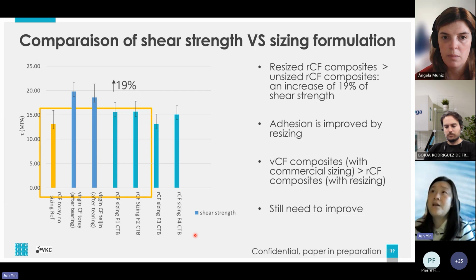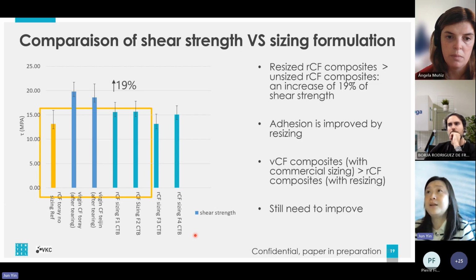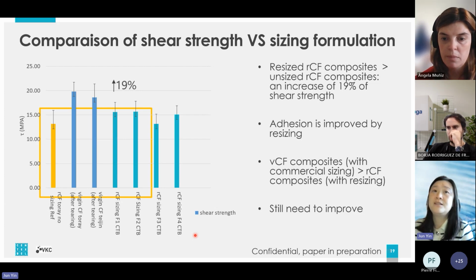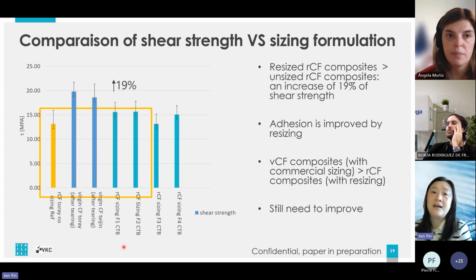The first is we can see clearly the resized recycled carbon fiber composite has a higher shear strength compared to the unsized recycled carbon fiber composite. We can see an increase of 19% of shear strength. So that means adhesion is improved by the resizing formulation. If we compare this recycled carbon fiber with virgin carbon fiber, yes, it makes sense. The virgin carbon fiber is higher than recycled carbon fiber, but that means we still have space to improve our sizing formulations.